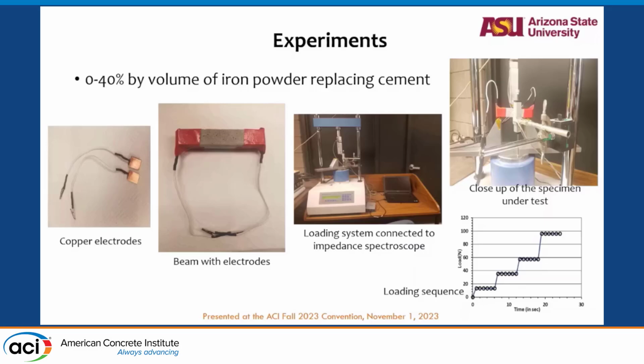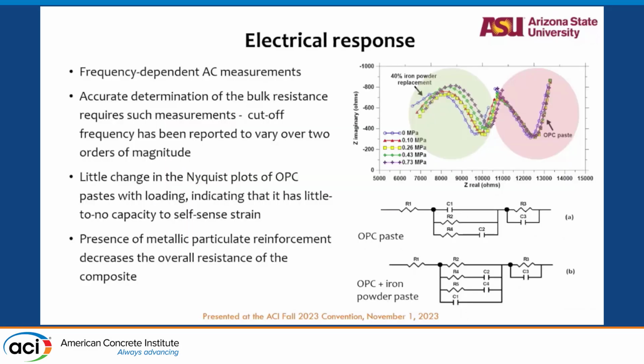We did stepwise loading, so that we have certain stress induced into the beam, and see if we can measure the resistance of the beam to figure out the strength of the sample. Initial observations are that, with iron powder being conductive, the resistance of the mix decreases with higher percentage compared to the OPC paste, and the decrease is significant for 40%, with 10, 20, 30% lying in between. Another observation is that for different stress states, for the OPC paste, the impedance and resistance are kind of clustered together. They are not as separate to distinguish between the different states. While for a higher iron powder content, the differences are quite significant, which we'll see later with different form factors also.